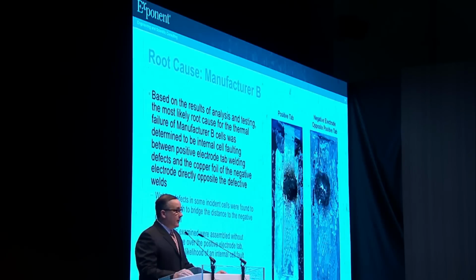In some samples that we examined, the layer of protective tape was missing, likely due to an error in the manufacturing process. In those cases, the probability of a short circuit was higher. The damage on the positive tab has a mating damage pattern on the negative electrode. This type of damage is characteristic of internal cell faulting. It can be seen that the damage pattern is closely associated with the ultrasonic welds.